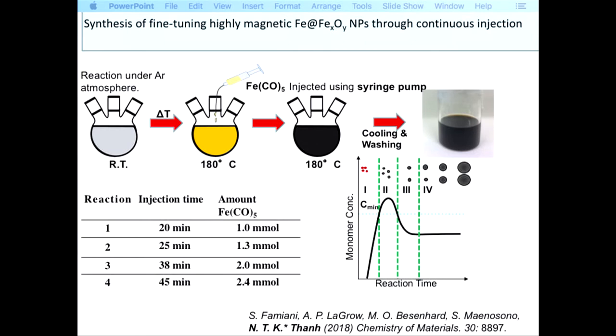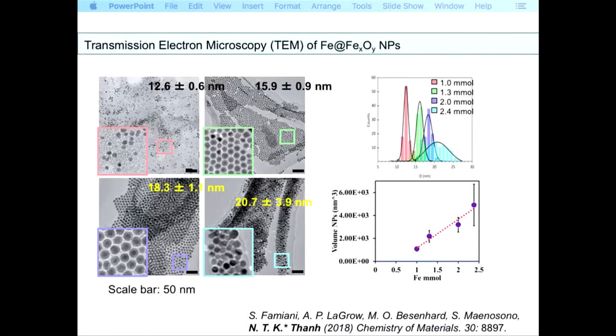We make them in hot organic solvent, and we add a precursor at different concentrations. As you can see here, if you have a higher concentration or higher amount, that means you are adding more, then it goes through the process of seed-mediated growth, and we get the particle getting bigger and bigger. And why is that? Because the oxidation consistently has the same thickness. So if you get a bigger particle, then you can save a bit more of the core, and that core is the highly magnetic iron nanoparticle.